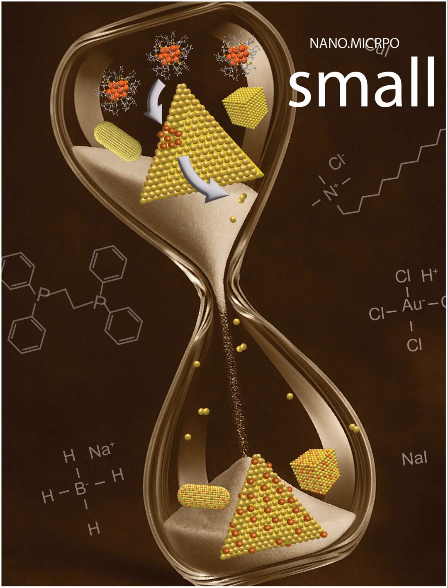So they can see where the gold is and where the copper is? Precisely. And what they found was a completely homogeneous distribution. Gold and copper mixed evenly throughout the entire volume. No sign of a copper shell around a gold core or anything like that, just a uniform blend. Okay, that's convincing. And they backed that up with another technique, ICP-MS, which measures the overall composition very accurately. That confirmed the average ratio was about 5.7 parts gold to 1 part copper in these final nanotriangles. So multiple different methods all saying the same thing.